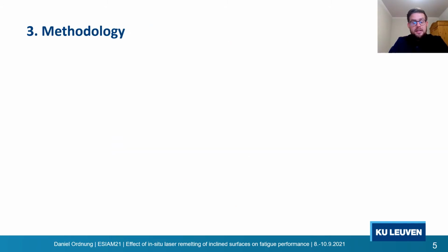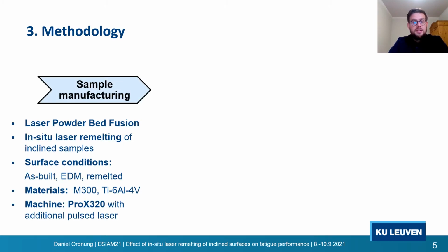The aim of this study is to improve the fatigue performance by laser remelting inclined surfaces. Therefore, we manufactured samples by laser powder bed fusion and processed the surface by this in situ laser remelting technique. To have a comparison, we also manufactured reference samples in as-built state and samples which were afterwards processed by EDM. We used maraging steel and titanium alloy powder and processed it with a special dual laser machine setup, which I will explain on the next slide.